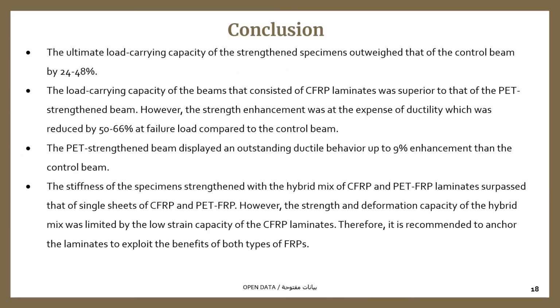Finally, the conclusion. The ultimate load carrying capacity of the strengthened specimens outperformed the control beam by 24 to 48%. The load carrying capacity of all the beams that consist of CFRP laminate was superior to that of the PET strengthened beam. However, the strength enhancement was at the expense of ductility, which was reduced by 50 to 66% at failure load compared to the control beam. The PET strengthened beam displayed an outstanding ductility behavior, up to 9% enhancement over the control beam.